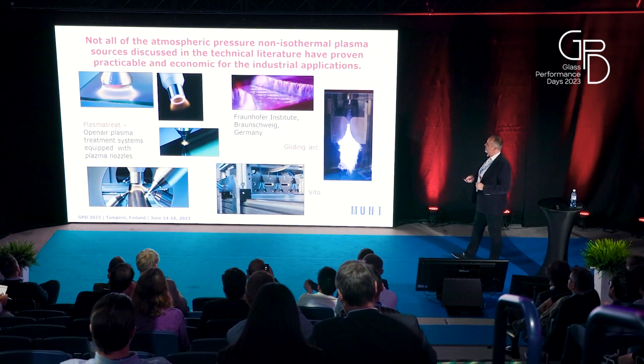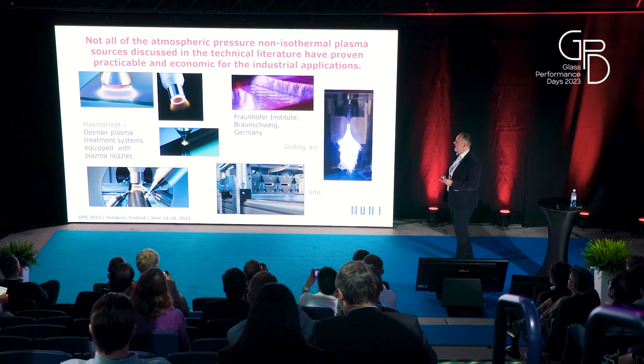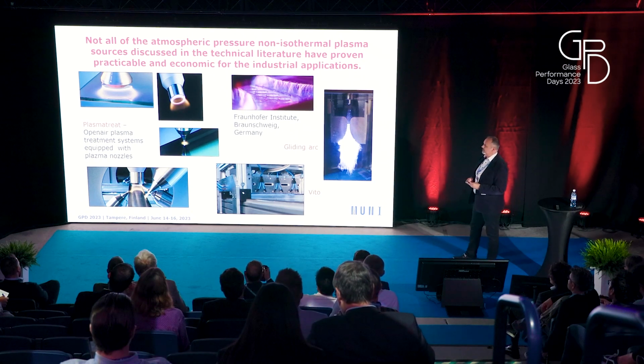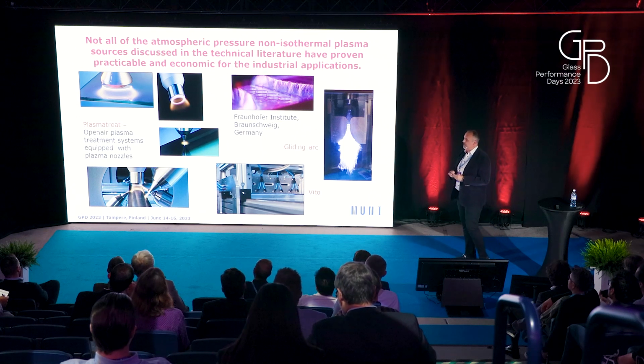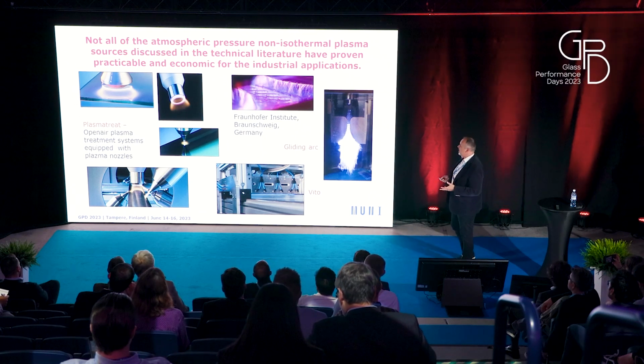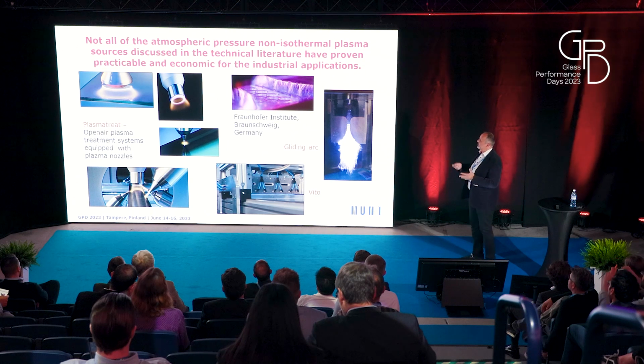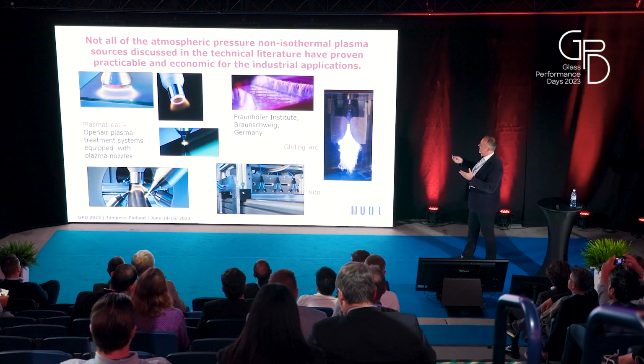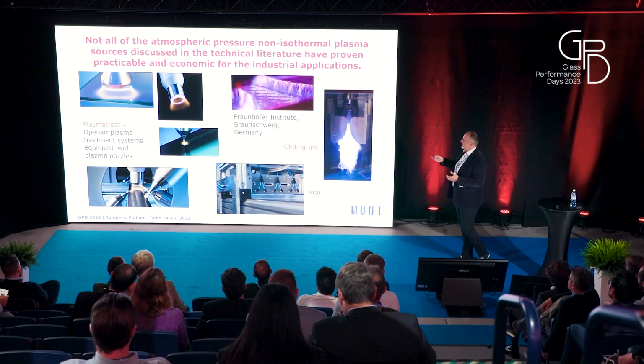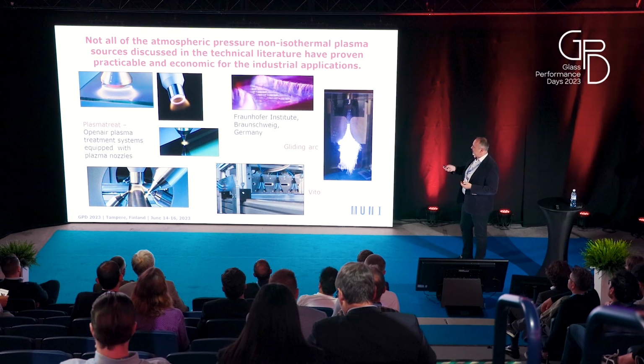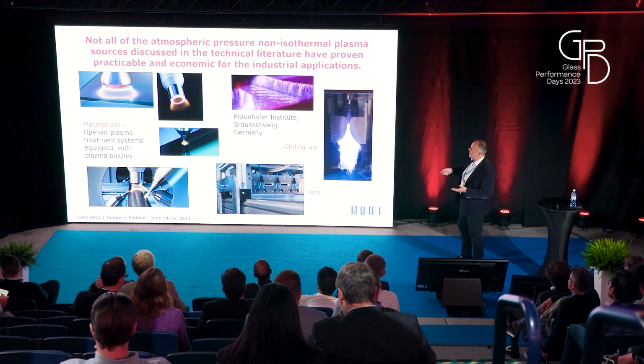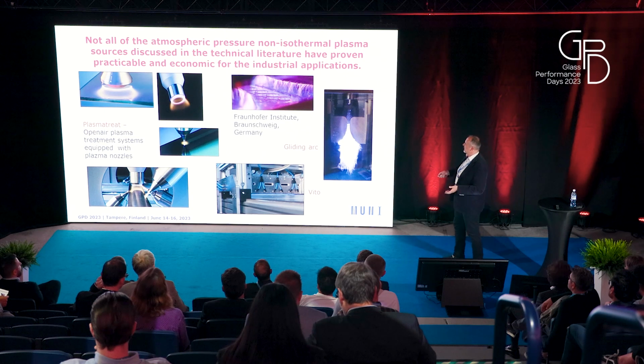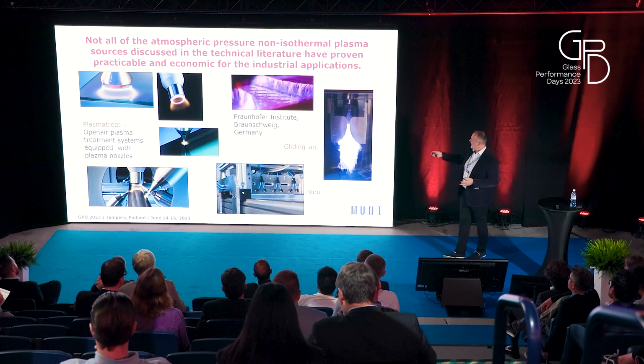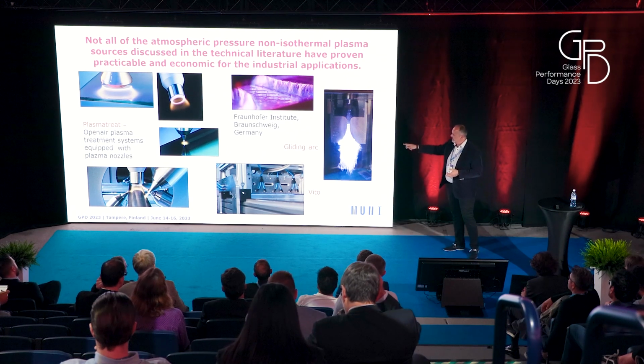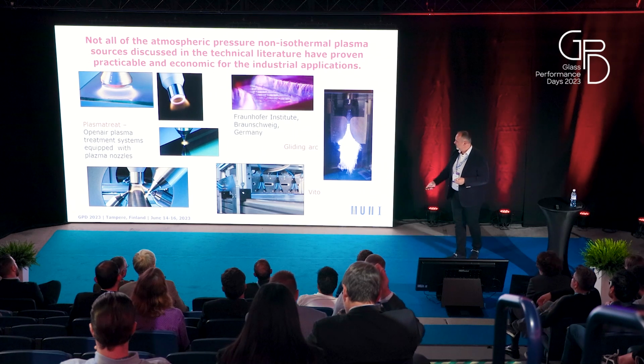If we want to treat the polymer interlayer at atmospheric pressure, we have to find a good and suitable plasma source. And it is not so simple, because it is possible to find different commercial plasma systems, but as you can see, they mainly generate a limited volume of plasma. They are using flowing gas for stabilization, or they are not sufficiently homogeneous, as you can see in this case of gliding arc.